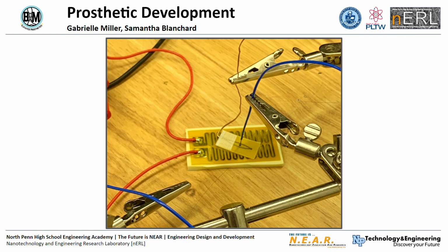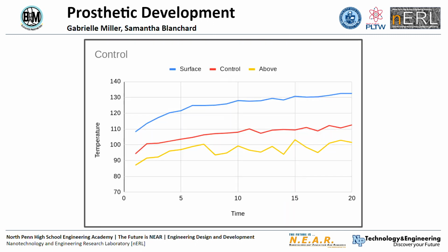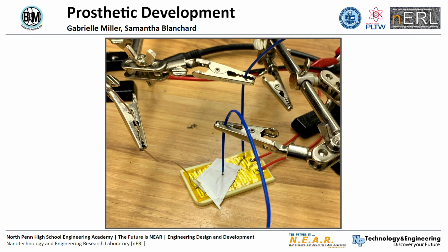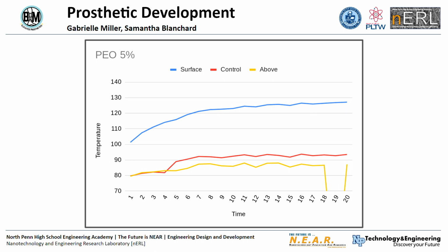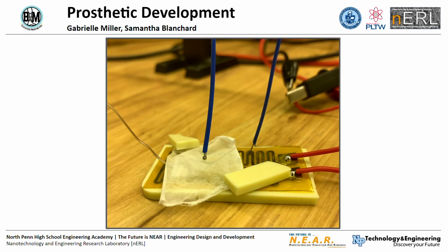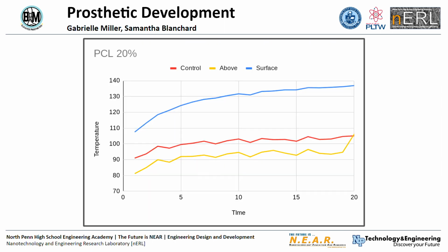Our first test was with our control, which had no polymer. Our average surface temperature was 123 degrees Fahrenheit, while our average air temperature was 95 degrees Fahrenheit. The next setup was using PEO, and the average surface temperature was 120 degrees, while the average air temperature was only 85 degrees Fahrenheit. And our final setup was with PCL, with an average air temperature of 90 degrees and an average surface temperature of 125 degrees Fahrenheit.